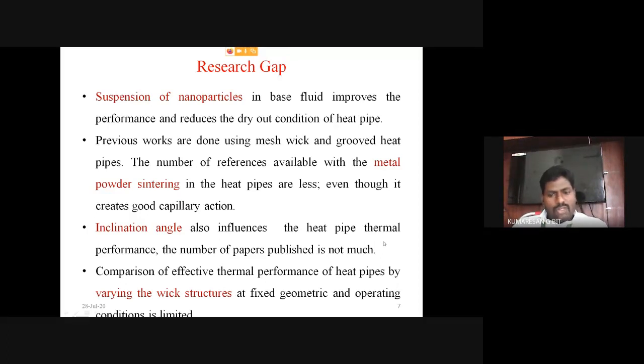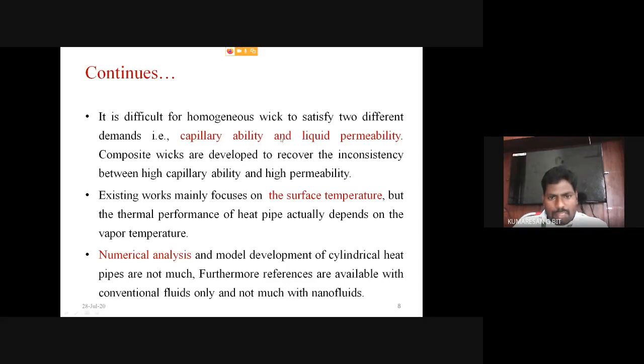Then, comparison of the effective thermal performance of heat pipes by varying the wick structure at fixed geometric and operating conditions. That means comparing the mesh, the sintered, and the combination of mesh and sintered wick structure, the performance of the heat pipe is analyzed at fixed geometric and operating conditions. Then this point I have already explained: capillary ability and liquid permeability. It is very difficult to attain these two parameters in a single wick structure. That's why I developed a composite wick structure to overcome these two problems.